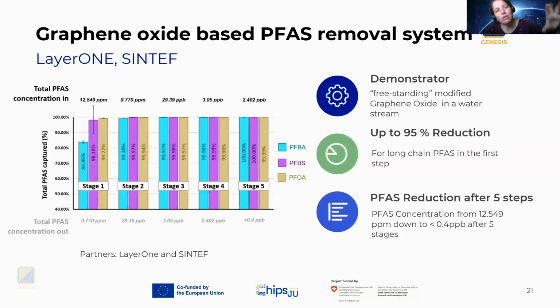And then they would like to reduce it further. That's why you have 4 more stages. So at the end, you have a PFAS level which is below 0.4 ppb. I mean, still, as Pedro said, there is not this one and only good value or threshold, that's true, but 0.4 ppb is much less compared with where it started. Basically, the less PFAS, the better. And this was done by partners in our Genesis project, so basically LayerONE and SINTEF. And with this, I would like to stop and we're open for questions.